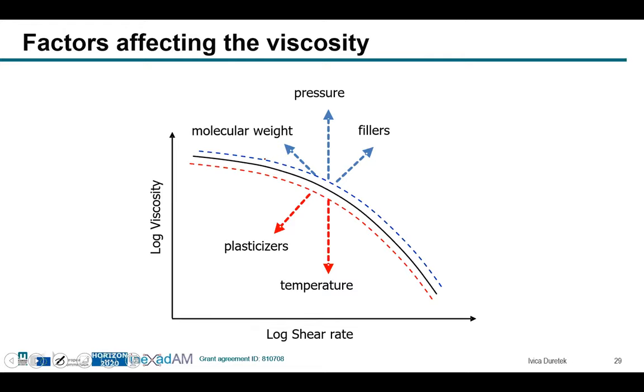This dependence is, of course, not linear. It would be very easy if we could say, okay, the dependence on the pressure is linear, and if you increase the pressure, for example by 100 bar, we can compensate this increase with an increase of the temperature. Of course, this is not possible.